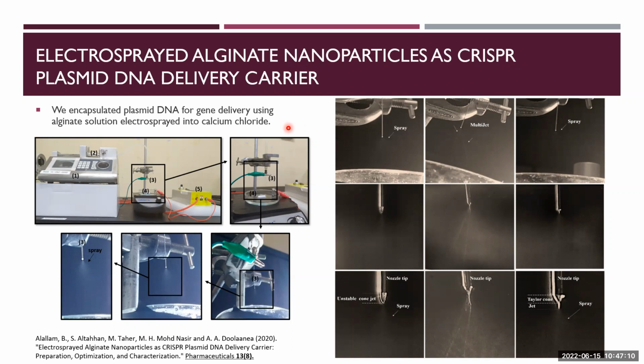But in another application, we encapsulated a hydrophilic material, which is DNA or plasmid DNA for gene therapy and gene editing. So the challenge with hydrophilic materials is that they are easy to dissolve in alginate, no problem, but the problem is that they will leak out when you cross-link alginate with calcium chloride.